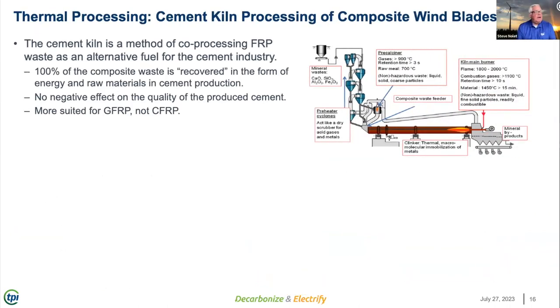Many of you may be aware of probably the most successful post-life process for wind turbine blades and scrap end-of-life composite materials. And that's the thermal processing of the material in cement kilns. The cement kiln method of co-processing is a true alternative. It consumes 100% of the wind turbine blade. Inorganic materials become part of the cement itself, the clinkers as they're called, and the organic materials, the adhesives, the bond paste, the resins of the matrix system, and our core materials become fuel for the kiln and reduce the coal necessary to be burned for the conversion in the cementing process.